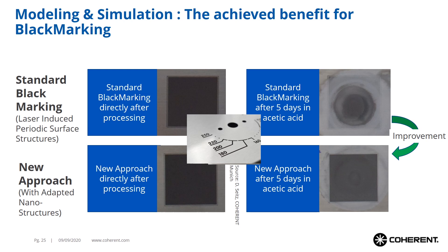Another success story: we took what we learned from the simulation of surface structure formation and tried to influence this formation to pronounce the blackening mechanism by structure. The structure offers a benefit oxidation cannot — acid resistance. A standard black marking put in an acid bath may disappear after a few days, which is undesirable for household items like a stove. With our improved nanostructure technique, we significantly improved acid resistance, and the picture shows impressively that the marking could still be read even after many swipes with acid cleaning agents.